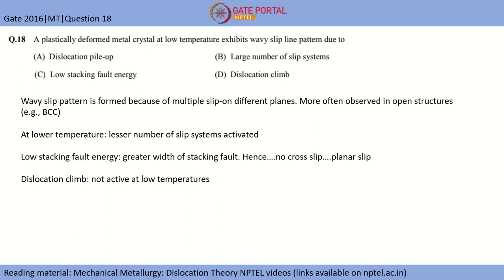Like one dislocation, if you consider this as a plane and this is one dislocation and this is another plane, this is another dislocation. So if this dislocation wants to go above the plane or below the plane beneath that, it requires certain temperature and movement of vacancies, and vacancies are a thermally activated process. Diffusion of vacancies is a thermally activated process. Hence dislocation climb is also not the reason for that.